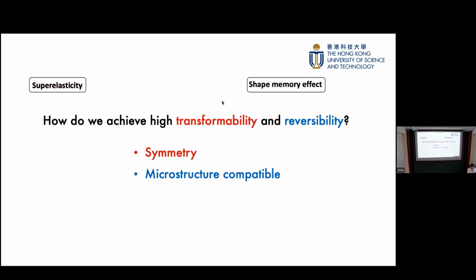And how do we achieve that? So we can design the material, we can design single crystals, and we can design the lattice parameters of the reference phase, austenite, the high symmetry one. And we can also design what it transforms to. It can transform to tetragonal from cubic. It can transform to monoclinic, even lower symmetry. And during this kind of reversible symmetry-breaking transformation, we can calculate the transformation stretch or transformation strain. And that actually underlies the total transformability of the material in a single crystal.